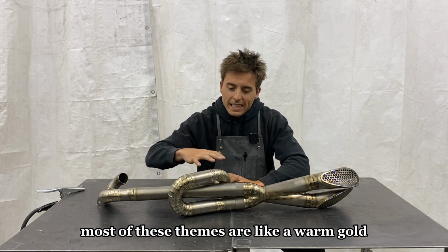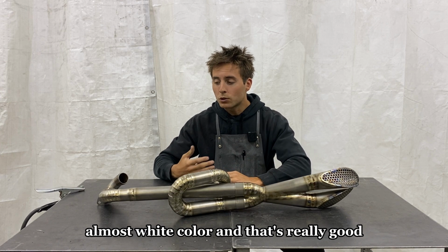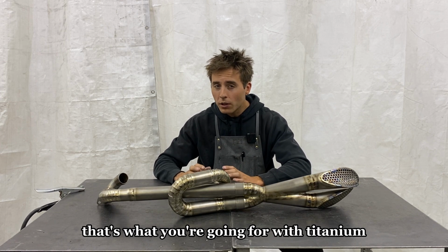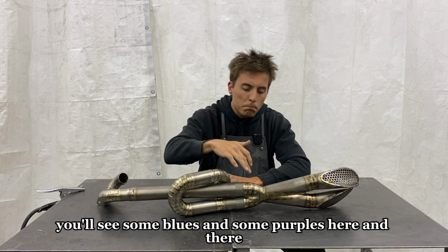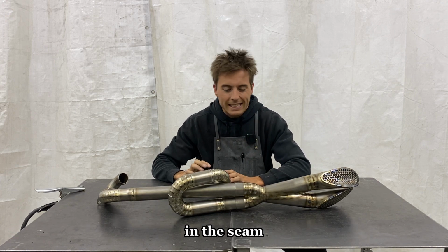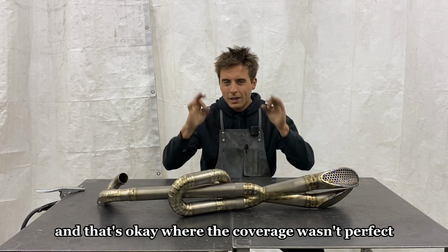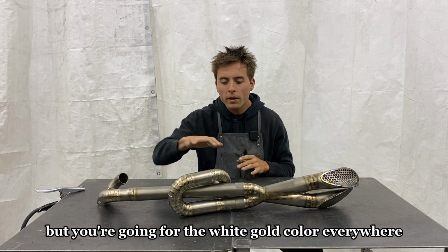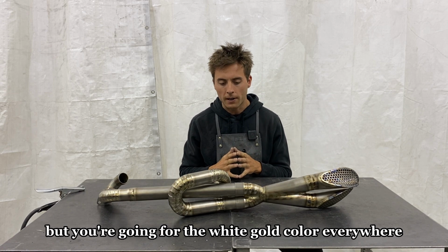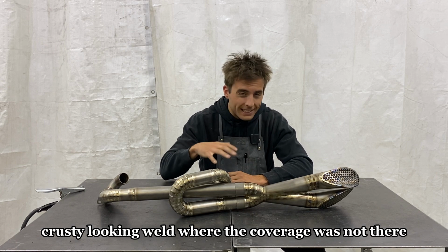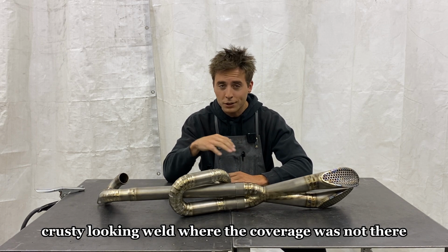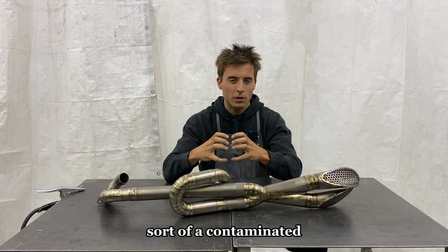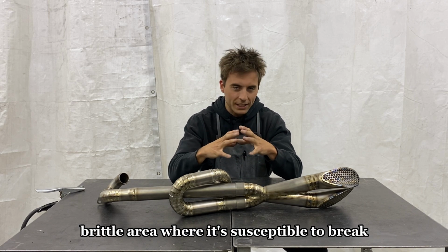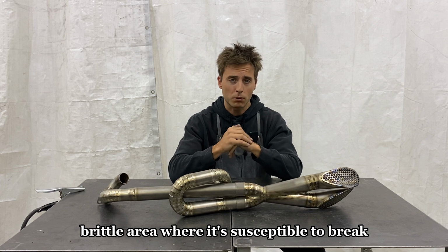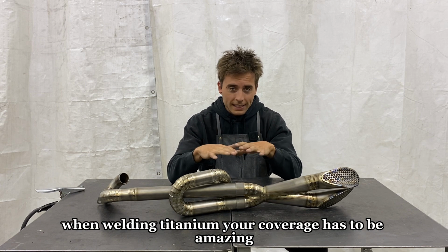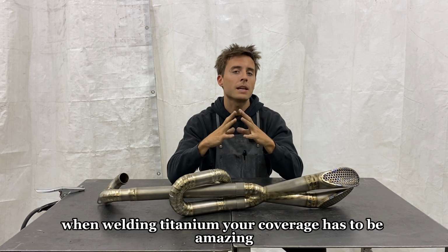As you'll see, most of these seams are a warm gold, almost white color, and that's really good. That's what you're going for with titanium. Now you'll see some blues and some purples here and there in the seam, and that's okay where the coverage wasn't perfect. But you're going for the white gold color everywhere. What you don't want is a gray, crusty looking weld where the coverage was not there. That's where you're going to get a contaminated, brittle area where it's susceptible to break. So to sum it up, when welding titanium, your coverage has to be amazing.